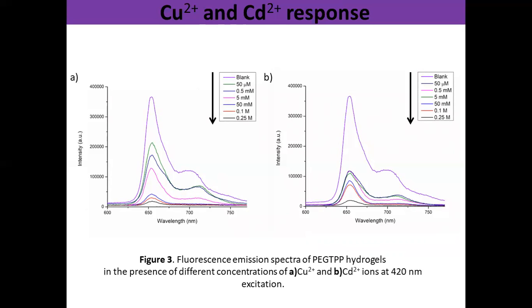For further study of the sensitivity of the metal ion detection of the PEG-TPP hydrogel, copper 2+ and cadmium 2+ were taken as an example, since these metal ions show the highest emission quenching. The fluorescence emission spectra of the PEG-TPP hydrogel in the presence of different concentrations of copper 2+ and cadmium 2+ ions are shown in figure 3. The reason for PEG-TPP sensitivity to metal ions copper 2+ and cadmium 2+ is ascribed to the functional groups of porphyrin included in the structure, and on the other hand, the high swelling of PEG-TPP makes metal ions penetrate inside of the hydrogel swiftly.